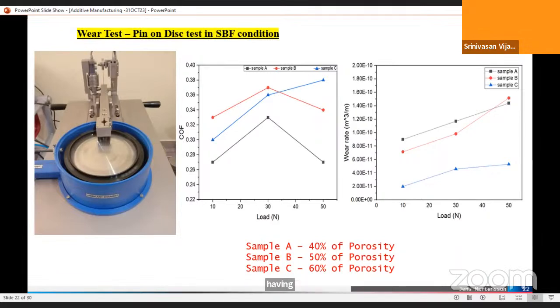Why? Technically speaking, people used to think that the coefficient of friction is directly proportional to wear rate, but that is not the case. Some of the detached particles might come into contact with the contacting asperities and act as a solid lubricant to reduce the wear rate. Generally, as a blind thumb rule, people used to say the coefficient of friction is directly proportional to wear rate. That is not the case in a pin on disc wear test, sliding wear test.